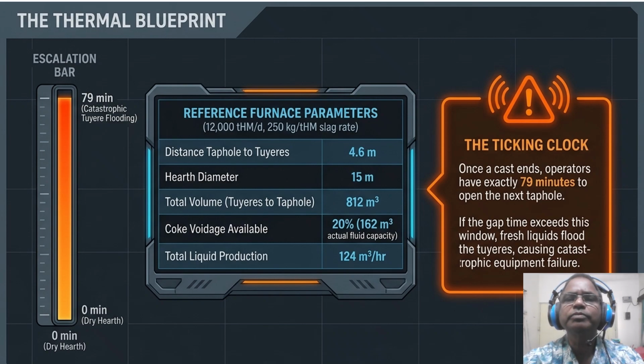Our total volume from the taphole to tuyere is 812 cubic meters, but because the hearth is filled with coke only, 20% of that, or 162 cubic meters, is actual fluid capacity. With a liquid production rate of 124 cubic meters per hour, your margin of error is razor thin. The operational impact is tremendous. So if your gap time exceeds 79 minutes, fresh liquid floods the tuyere, causing immediate equipment failure and multi-day outages.